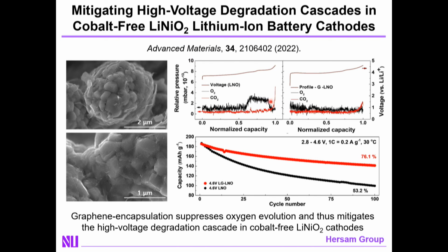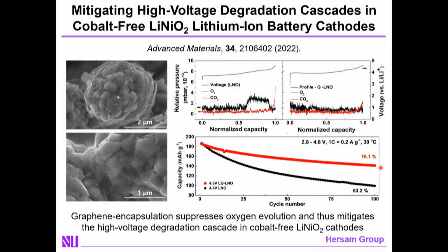You can see this very clearly in mass spec. At high states of charge, you see oxygen coming out of your electrode. This leads to a cascade of problems, ultimately leading to a short lifetime of the battery. In contrast, with the conformal graphene coating, you get essentially a hermetic seal on the surface. It creates a large barrier for oxygen evolution. You no longer see it removed at high states of charge, and correspondingly, you get a much higher cycle life.